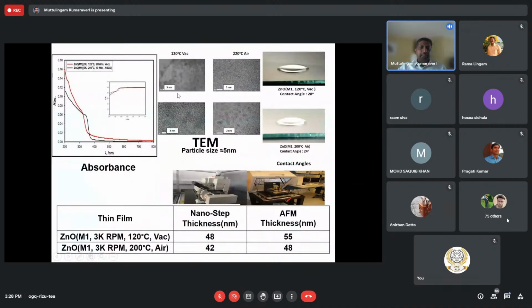Okay, now the films we made, two films. One is annealed at 120 degrees, and the other is annealed at 200 degrees in air. So there is the UV absorption plot. You can see the red one is the 120 degrees annealed, with high absorption, and this one has a little bit lower absorption when annealed at 200 degrees. And also the TEM, you can see both. The particle size is around 5 nanometer from this dispersion.